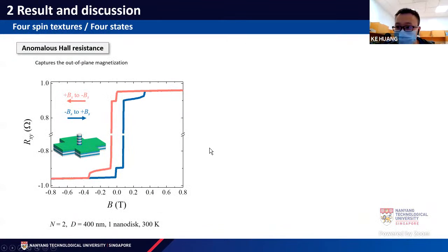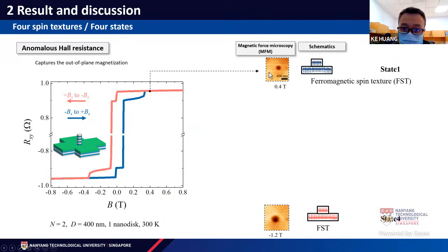Since the nanodisk is very small, less than 1 micrometer, the general MOKE method cannot give a very accurate result. So we choose to use the anomalous Hall effect, and we were sweeping the field. We can observe this hysteresis, but it has multiple switches. If we want to know what the spin textures are during each step, we use another technique, MFM.